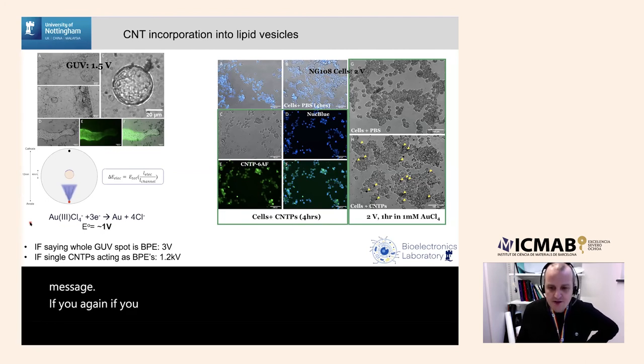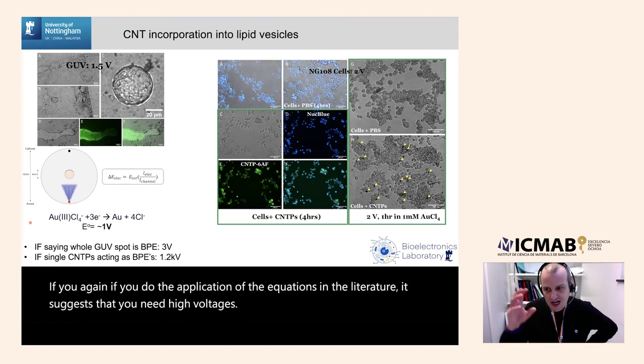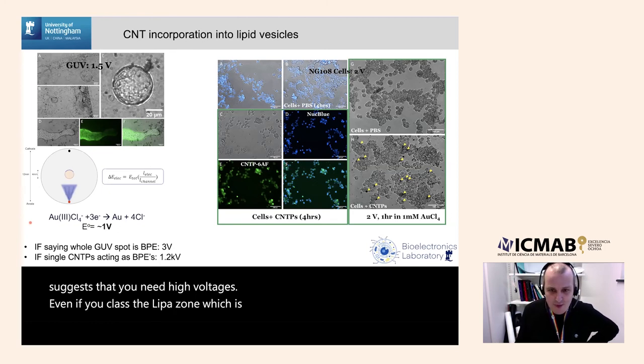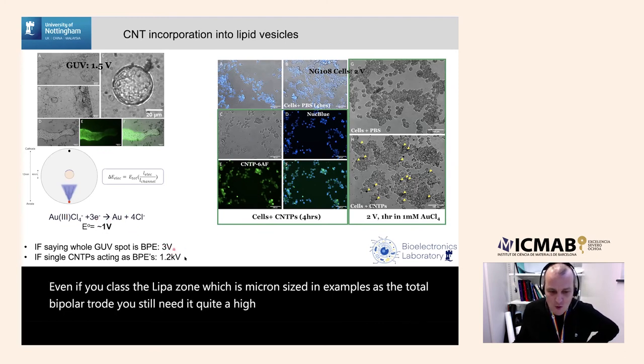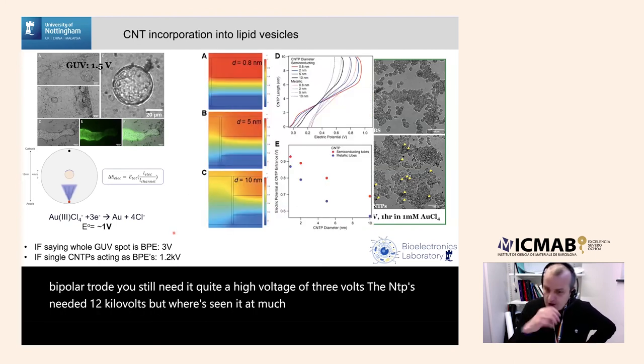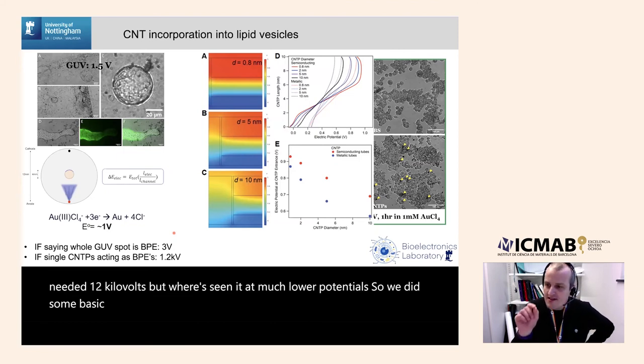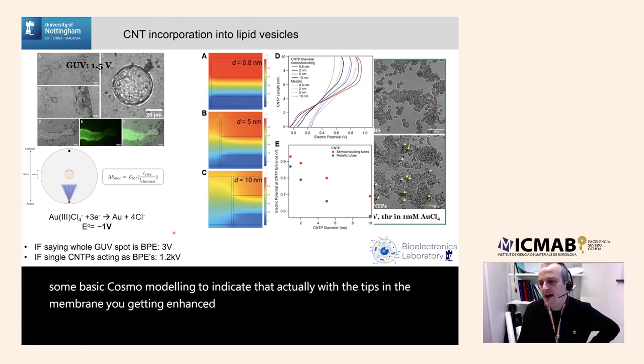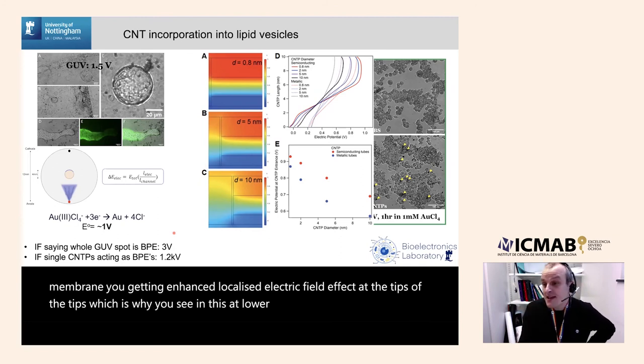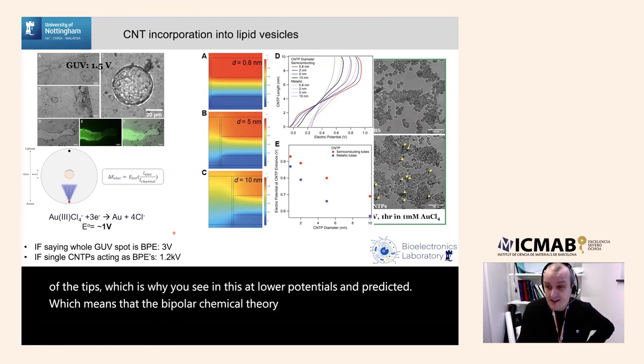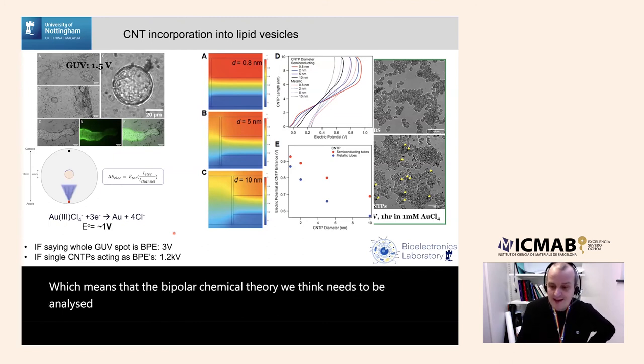But just a take home message, if you do the application of the equations in the literature, it suggests that you need high voltages. Even if you class the liposome, which is micron sized in examples, as the total bipolar electrode, you still needed quite a high voltage of 3 volts. The CNTPs needed 1.2 kilovolts, but we're seeing it at much lower potentials. So we did some basic COMSOL modeling to indicate that actually with the CNTPs in the membrane, you get an enhanced localized electric field effect at the tips of the CNTPs, which is why you're seeing this at lower potentials than predicted, which means that the bipolar electrochemical theory, we think, needs to be analyzed again to take this phenomena into account.